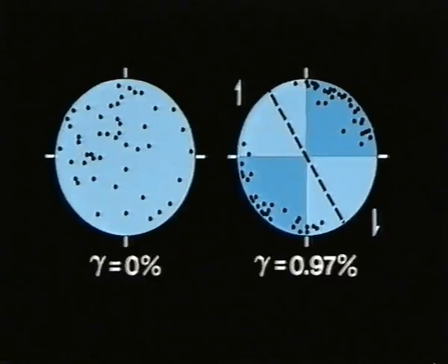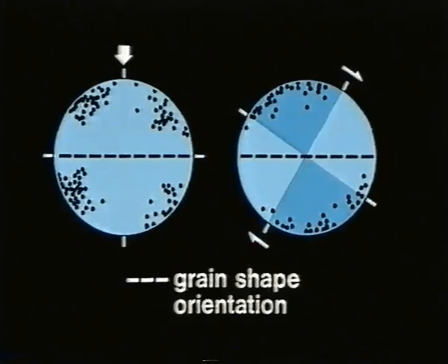The C-axis fabrics observed here are consistent with the C-axis fabrics measured in natural ice. They are also comparable with crystallographic fabrics recognized in other mineral aggregates, particularly those that have undergone simple shear where one glide plane is dominant, as in the case of quartz. It should also be noted that the single maximum pattern developed in simple shear is in marked contrast to the double maximum pattern that we saw developing in pure shear.